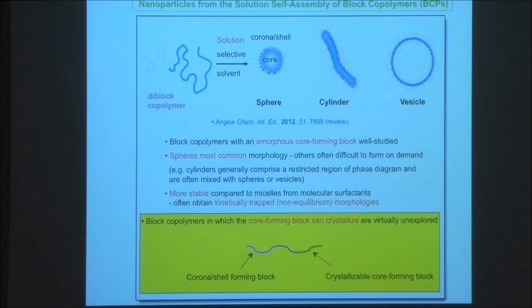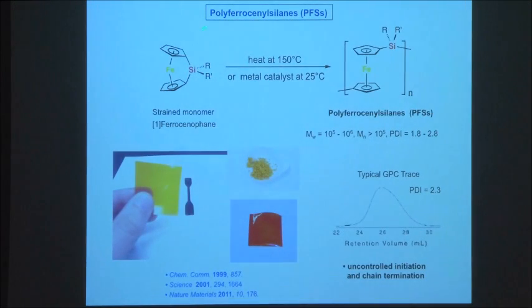Now, we actually got into this area by looking at block copolymers with a crystallizable core-forming block, which was based on one of the metal-containing polymer systems that we've developed in our group over the years. And this is the polymer system. It's called polyferrocenylsilane, or PFS. And this is the structure. So it's a metal-containing polymer. It contains metal and silicon. And these materials are made by ring-opening polymerization of these strained monomers. So these are very easy to make.